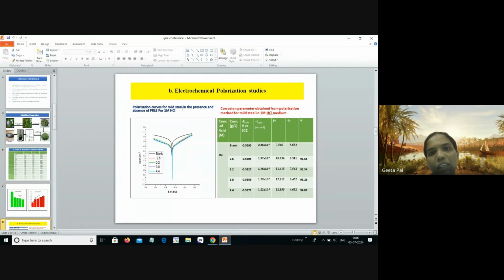Then it can be further confirmed by the electrochemical studies as well as the potentiodynamic polarization technique. Electrochemical impedance spectroscopy is the most effective technique, which is used for determining the corrosion kinetics as well as the corrosion potential value. From the result, it can be concluded that the electrode potential value is almost constant for all concentrations of the inhibitor. Whereas on the other side, the corrosion current density value goes on decreasing. It indicates that in the absence of the inhibitor, the corrosion current density value is high, whereas in the presence of the inhibitor, the corrosion current density value is low.